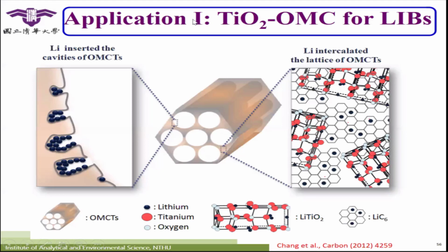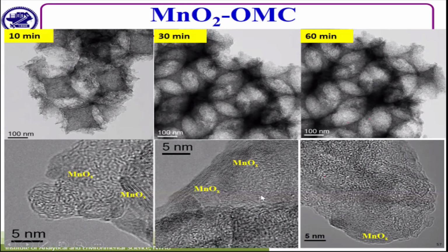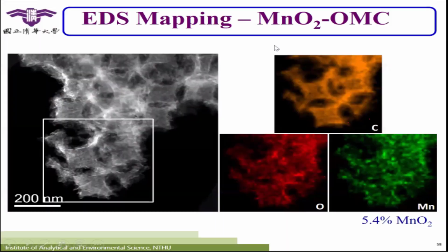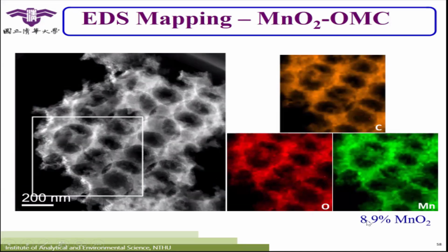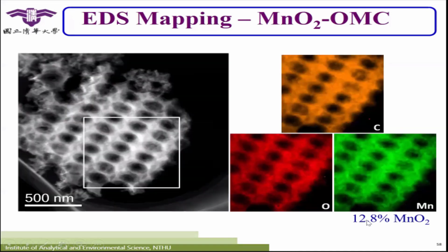We can put MnO2 inside here, and you always will see this using EDS mapping of the highly ordered mesoporous carbon with MnO2. When we add 5.4% of MnO2, the case is here. 8.9% is here. 12.8% of MnO2 is here. You always will see that carbon, oxygen, and manganese are all the same.